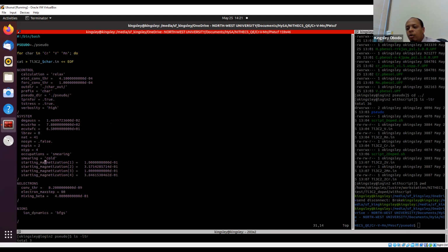And then I wanted magnetization in my system because I explained a priori that we are working with magnetic systems. So you introduce static magnetization; if you do not do this, your calculation would have a problem. My number of atom types is 4. The reason is because we have titanium, carbon, and hydrogen, and then we introduced a dopant on the titanium side. So now the number of atom types you have is 4. Your number of atoms is 41.